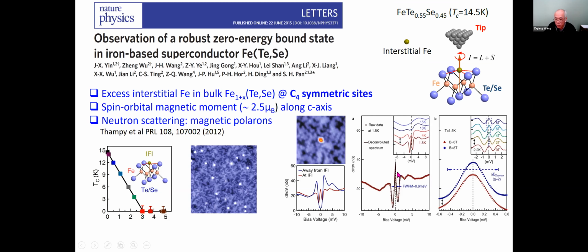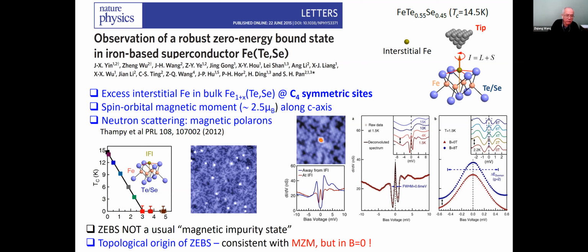In fact, this is a zoomed in picture. This is a robust zero energy peak that only sets in below the superconducting transition. And it's robust against the magnetic field. And there is even other evidence that tells us this is not a usual magnetic impurity state. It's got a kind of topological origin. And in fact, if you look at all the spectroscopy properties of this zero energy state, it is consistent with a Majorana zero mode, but in zero magnetic field.